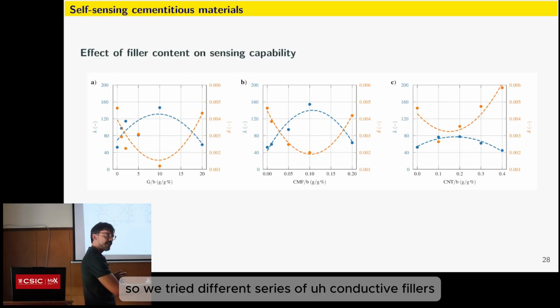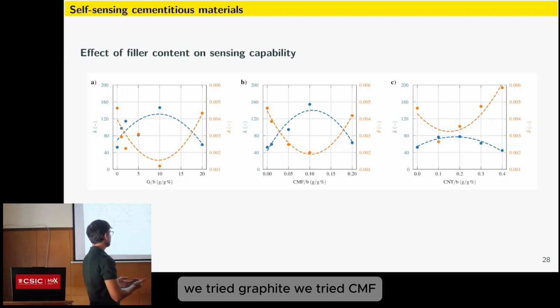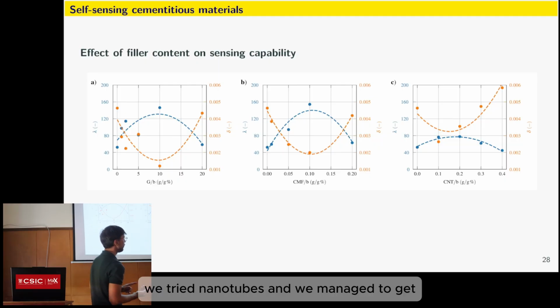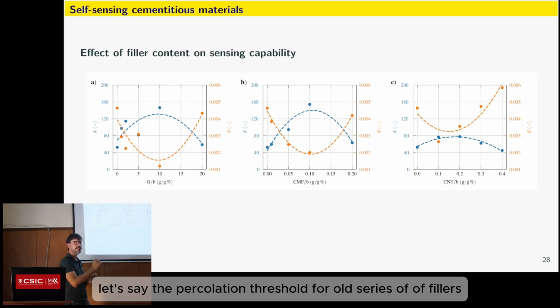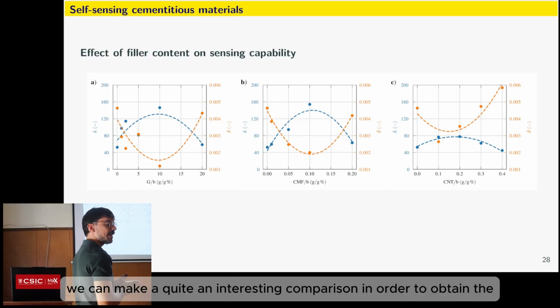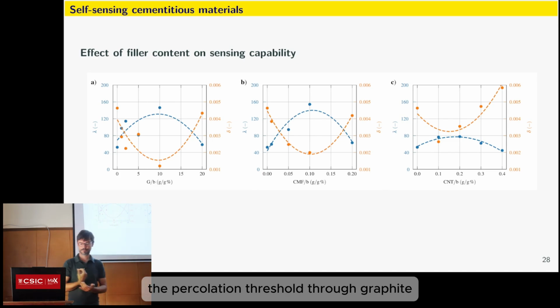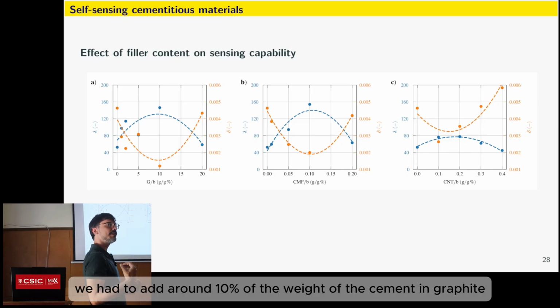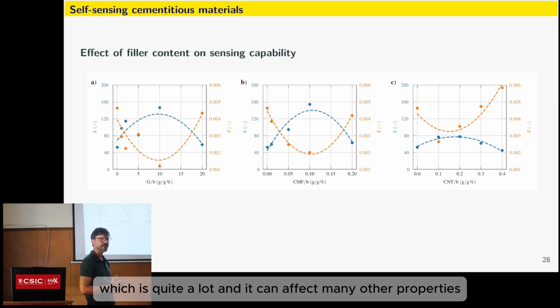So we tried different series of conductive fillers. We tried graphite, we tried CMF, we tried nanotubes, and we managed to get the percolation threshold for all series of fillers. So we can make quite an interesting comparison. In order to obtain the percolation threshold through graphite, we had to add around 10% of the weight of the cement in graphite, which is quite a lot, and it can affect many other properties.